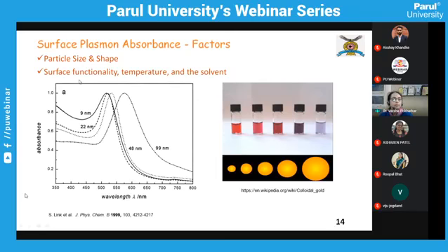the surface functionality on the particle surface, the temperature and the solvent that is used during the synthesis. If we look at a simple UV-visible spectrum, this is a typical surface plasmon that we will get depending upon the size. As the size increases, in this picture you can see from 9 nanometers to 22 nanometers to 48 to 99 nanometers, there is a shift in the lambda max of the surface plasmon band.